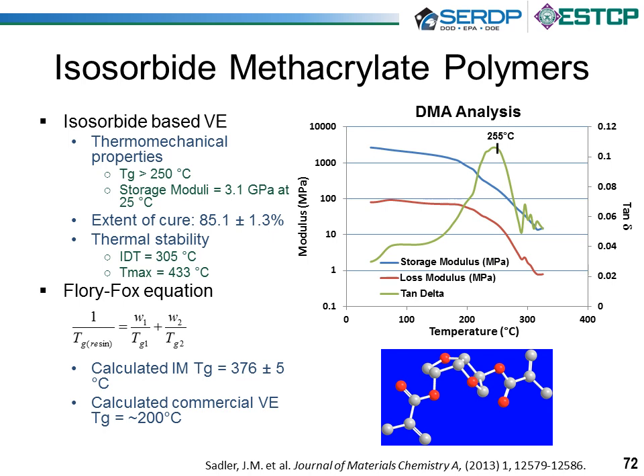The modulus was 3 gigapascals at room temperature, which is great, but the glass transition temperature, as shown by that green curve on the plot, the tan delta, was over 250 degrees Celsius, which is far higher than that of any commercial vinyl ester. High-temperature commercial vinyl esters, we're talking 180 degrees Celsius. So this is an example of bio being able to be used to make higher performing materials than conventional materials.